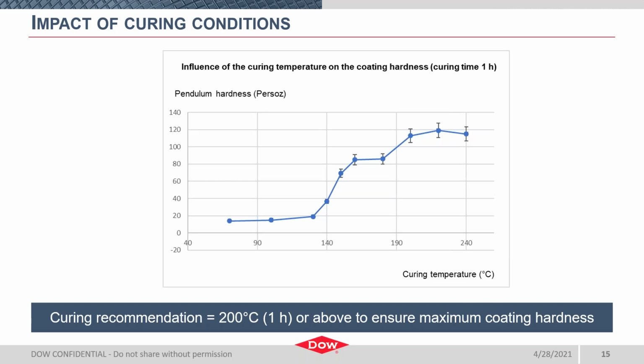Continuing to talk about cure temperature. This is a more holistic view of the influence of cure temperature on coating hardness or film development. Aside from our theory-based recommendations and historical guidelines, this gives us a really good idea of the temperature range required to trigger that full cure in an oven by measuring hardness. On the y-axis is the pendulum hardness, and on the x-axis is the curing temperature, increasing as you move from left to right. For all of the cure temperatures in the study, the cure time was held constant at 1 hour, so consistency maintained again.